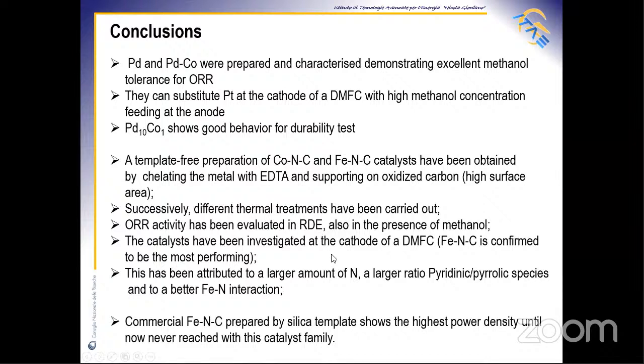In the second part, a template-free preparation of cobalt NC and FeNC has been obtained by chelating the metal with EDTA and supporting on oxidized carbon. Different thermal treatments have been carried out, and the activity in oxygen reduction reaction was evaluated in rotating disk electrode tests and with the direct methanol fuel cell at the cathode of this cell. The FeNC is confirmed to be the most performing catalyst, and this has been attributed to a larger amount of nitrogen, a larger ratio of pyridinic pyrrolic species, and to a better iron-nitrogen interaction.